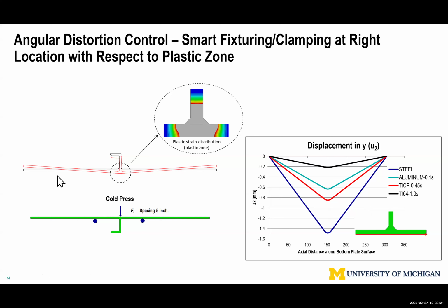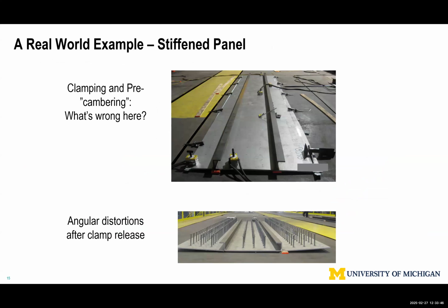The only way for that to work is to put a clamp down only vertically, as close as possible in this neighborhood. It doesn't matter what steel, aluminum alloy, or titanium you are dealing with. The magnitude varies, depending on material property, but the trend is identical. That means the same methodology can be used for different materials and different structural elements. To demonstrate that, here's an example. It's a shop floor example.